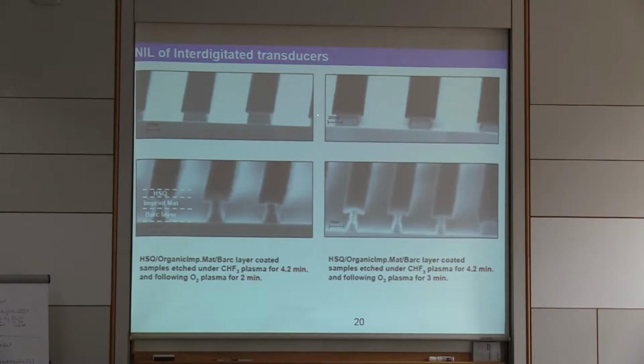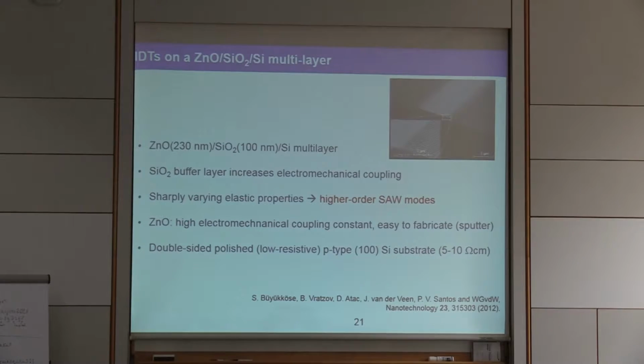of these fingers or test structures, and you clearly see, depending on the etching time, you can have more or less undercut. So this is a bit longer etching, and you really see that at some moment you even start to remove completely the organic material. So you have to be careful there. But the good thing is that no matter how long you etch, this width is constant in principle. Okay, so that's about how we make the things.